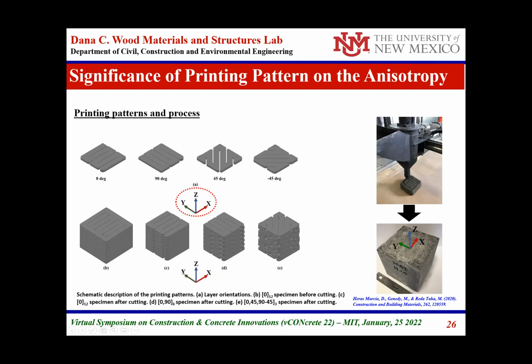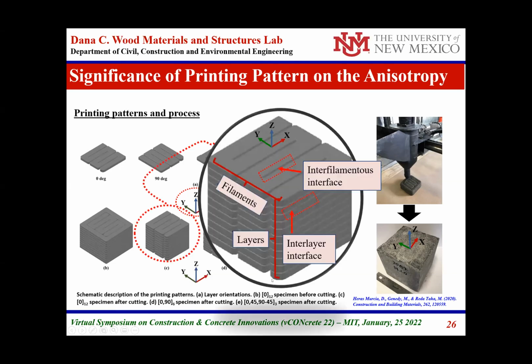We printed in the different directions and quantified the concrete strength and modulus. In these properties we identified a few variables: the filaments, the layers, the voids between layers which is the interlayer interface, and the interface between filaments which is the interfilamentous interface.